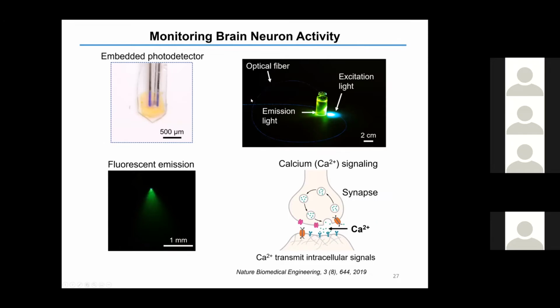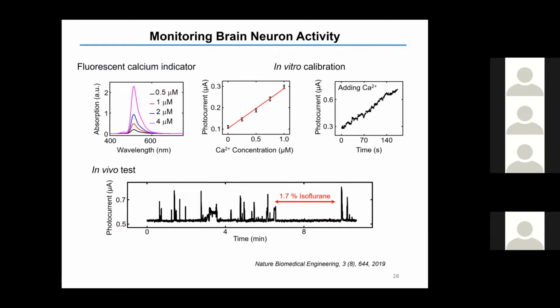So we integrate the bioresorbable optical filter into the transient optical probes. When the probe is immersed into a green fluorescent solution and the fiber delivers blue light, the photodetector embedded underneath the optical filter can only respond to the emission of green fluorescence light, which is proportional to the concentration of calcium ions, an important neuron indicator. The response is in a relatively linear fashion and relevant to the physiological range in the animal brain.